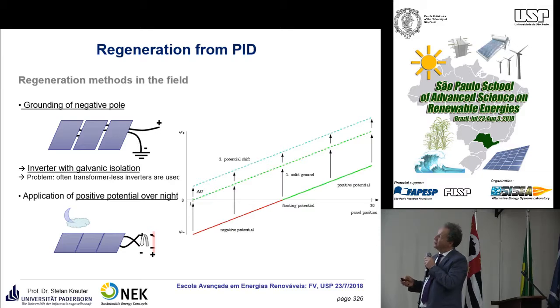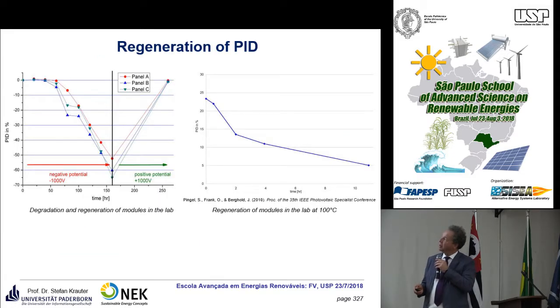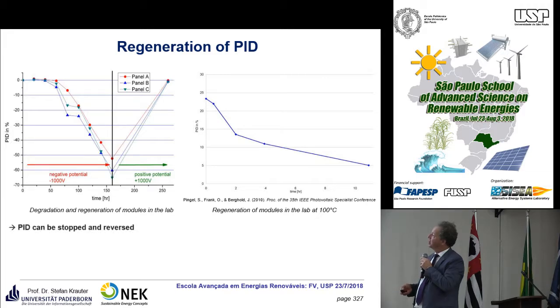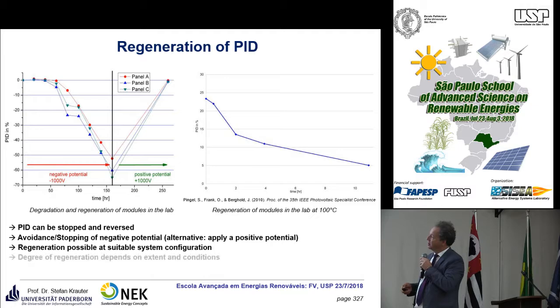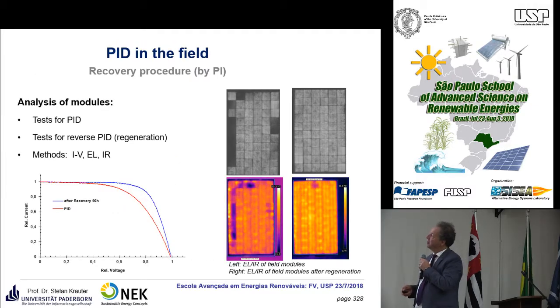You see the grounding of the negative pole also helps, so we just avoid the negative polarity here, and also if it's not possible, this depends, or if you don't have a transformer, if you're a transformer-less inverter, which becomes more fashionable at the moment, becomes much cheaper, then this is not suitable to ground it. You check it first. What you can do then is to reverse voltage, to put a different voltage in nighttime there, and then you can reverse that effect. This can cause regeneration from a PID effect here on the module level. So this is some things we carried out research here. PID can be stopped and reversed.